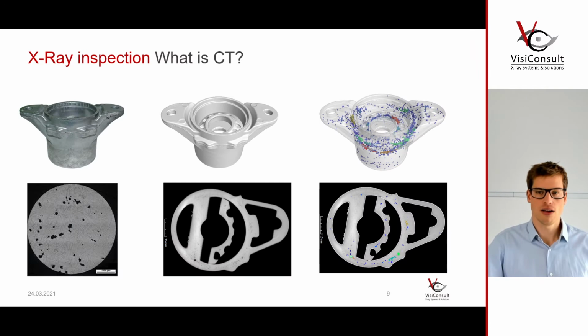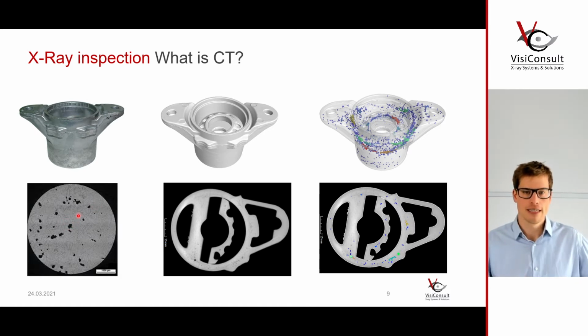So how do we get along? And of course, what you can do in the lab is that you can take your part, you can cut it open, you can do a metallographic analysis under a microscope, and you can look at porosities, you can look at cracks, you can look at inclusions. That's all traditional. But if you do that, your part is cut. It's destructive testing. It's not doing you any good for production. You can do this with a sample, but you can't do this with every part you produce.